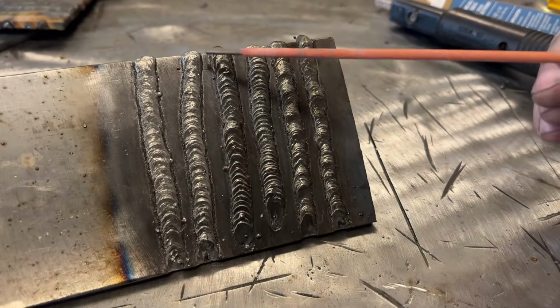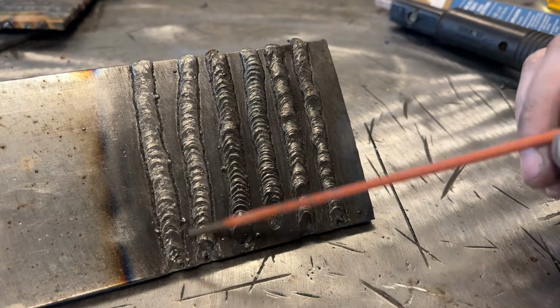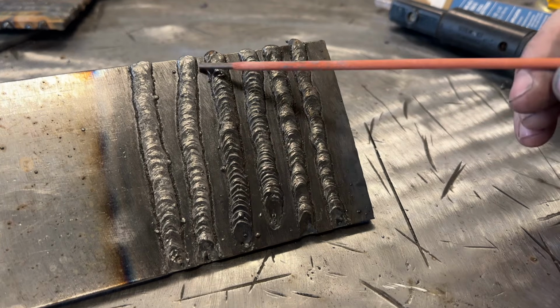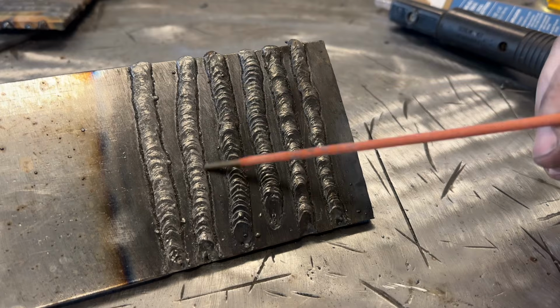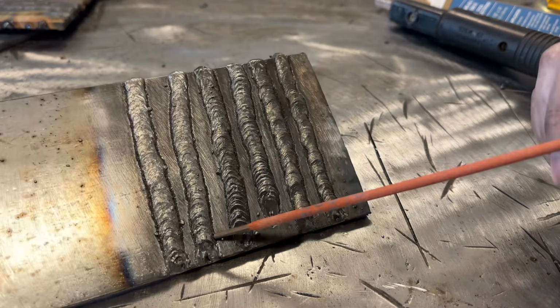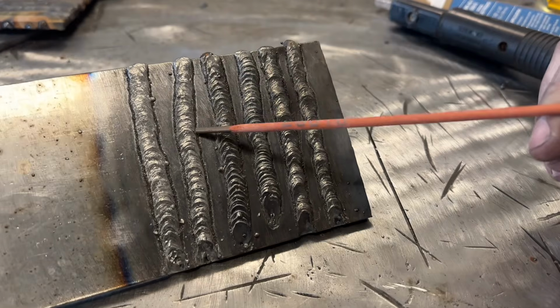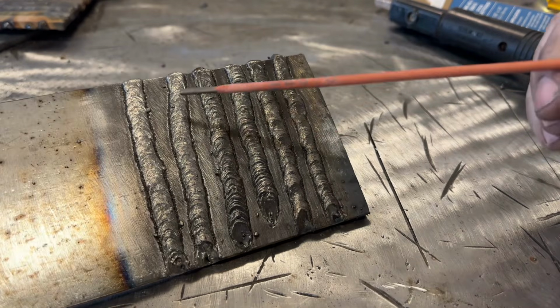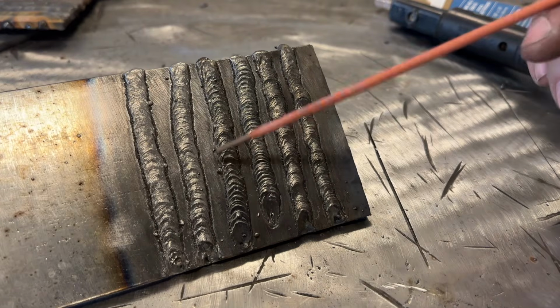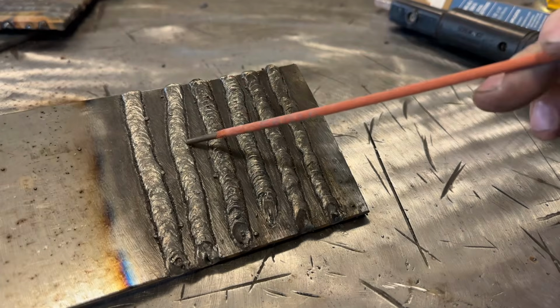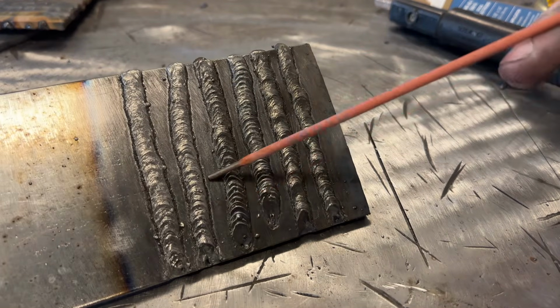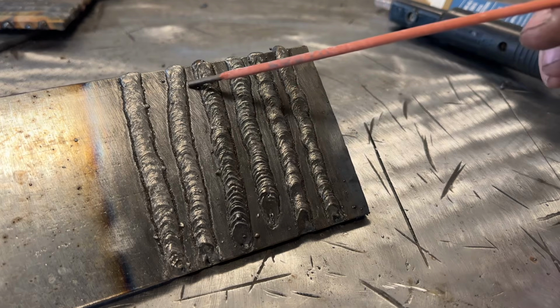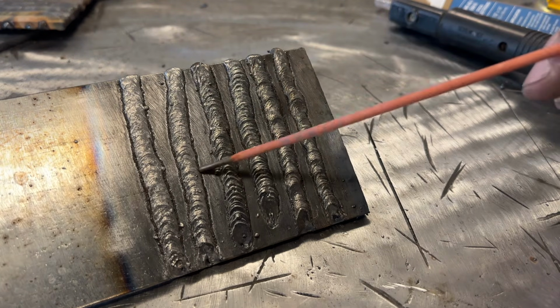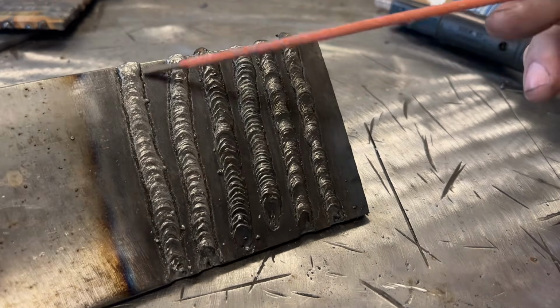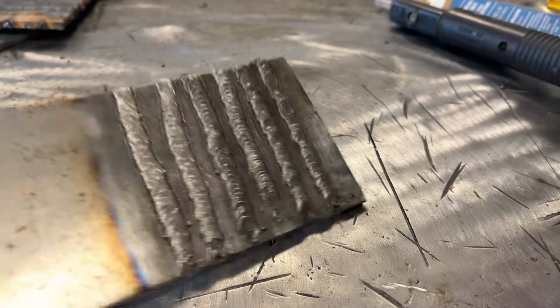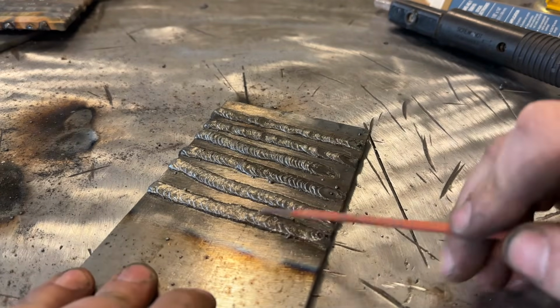When you do multi-pass welds, and say you did a root pass, and then you had to do 3 more over that, if you just come in here and weld right over this, especially with 7018, you can entrap that slag and you get what's called wagon wheel tracks on the x-ray. You basically bust x-ray because down the whole weld, you'll see a line that follows this because you don't burn this out. Now, if you're doing multiple passes with 6010, you probably will burn that out, but it's hard to say. So my recommendation, and I wire wheeled this on a grinder, and you can see it left this here. And I'm going to show you that that does come off.